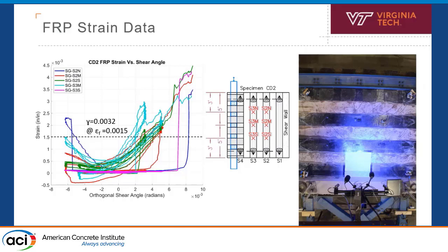So you can see those Sharpie lines are a lot bigger than what you actually see. Those cracks are small. They're in between the sheets. Nothing's blowing up, so you're good there. And so we instrumented two of the sheets with three strain gauges each, so six total, five were functional. And out of those five, we did get to 0.004 on some of them, and those are the ones that debonded at failure. If you can see, those are on the south end of the slab, which is where those did debond.